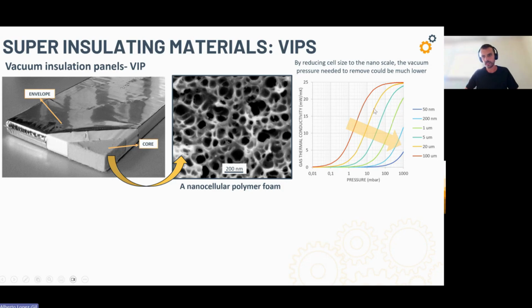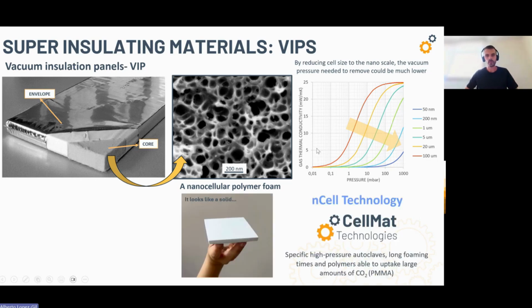By doing this, as you can see here in this graph, where we see the gas thermal conductivity and the vacuum pressure, by reducing the cell size from 100 microns to 50 nanometers, which is this line, we can reduce enormously the vacuum needed. So now the energy required to produce the vacuum insulation panel is lower. And this is something we have already done.